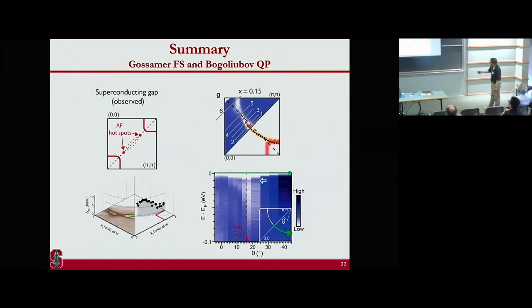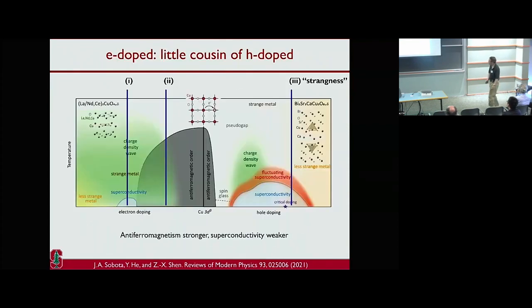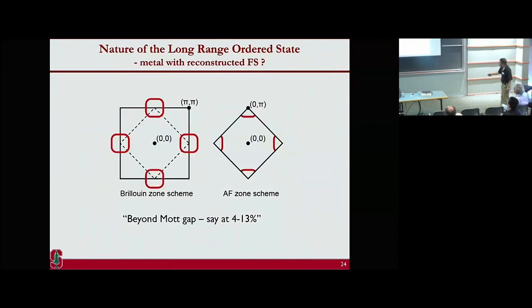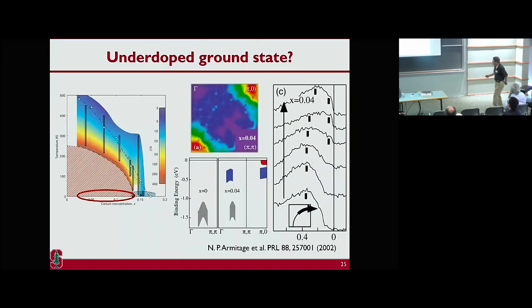Again, the data I hope you see is very clear. There's two features. There's one, and there's another one, and that's the lower energy one. So let me now talk about this one. This is in the regime of the long-range ordered state. That is what you would have expected. I want to say that I'm talking about 4% or above. So that's sort of the other piece of Fermi surface, now below the Fermi level.